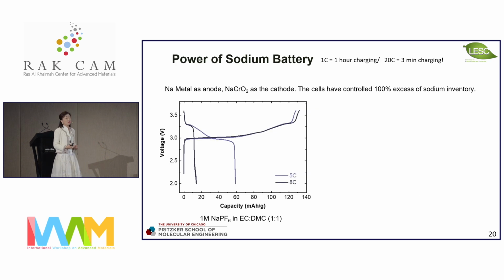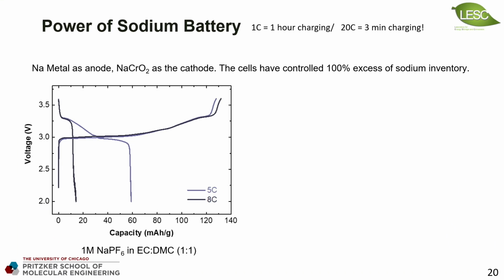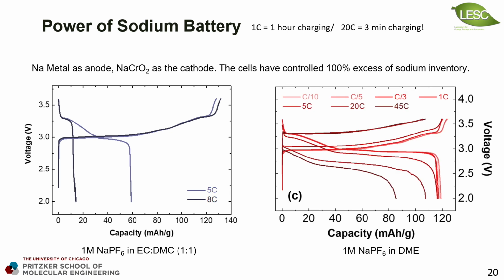So sodium batteries, do we really do it because it's inferior to lithium? So I will show you an example here. We are using here sodium metal as the anode and sodium chromium oxide as the cathode. And here I ramp the charge rate very high. 5C means 12 minutes charge discharge. 8C means 7 minutes charge discharge. So the first trial with the electrolyte I just took from lithium, and then I switch the salt to sodium. Okay, it's not the best, right? In the new electrolyte, sodium batteries can enable 3 minutes or even 1.5 minutes fast charge and discharge.